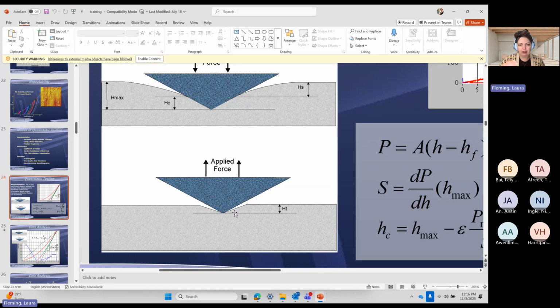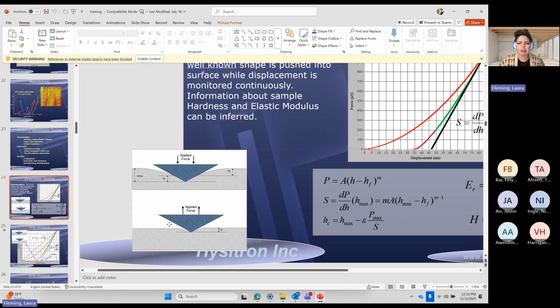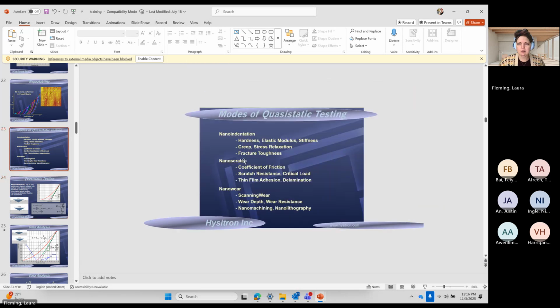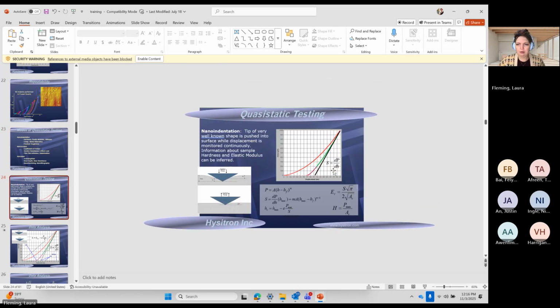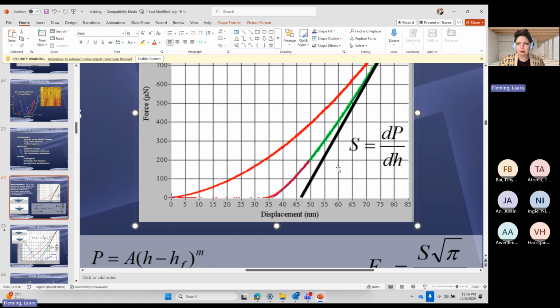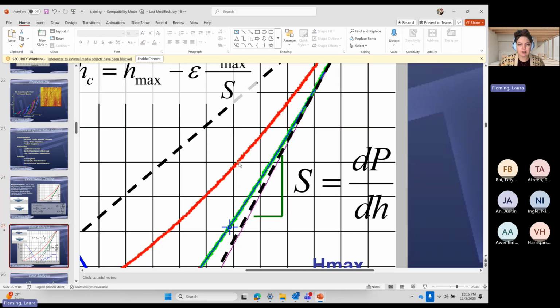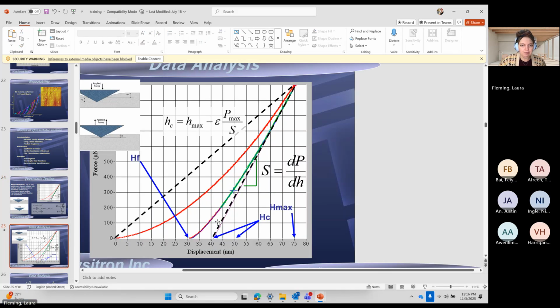Then, as it removes itself from the material, you get your final plastic deformation into the sample surface. So if we look at this graph, that's what we're looking at here. Actually, this one has a better image of it. So here's our fit. You get our stiffness. You get your contact depth, where that stiffness fit intercepts the x-axis. This is your final displacement, meaning when the tip is coming out of contact, when the force goes to 0. And here's your maximum depth, so how far that probe got into the sample surface completely.